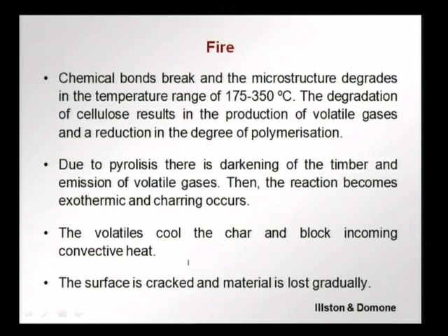Due to pyrolysis, that is the action of the fire, there is darkening of the timber and further emission of volatile gases. Then the reaction becomes exothermic, that is, the wood starts to burn, and the result is charring, or the formation of charcoal on the surface. The volatile gases coming out of the burning wood cool the charcoal and block incoming convective heat. So, it starts insulating the inside of the wood. So, the charcoal protects the inside of the wood to some extent, and as long as sufficient wood is inside your structural element, there is no collapse or breakage of the structural element.